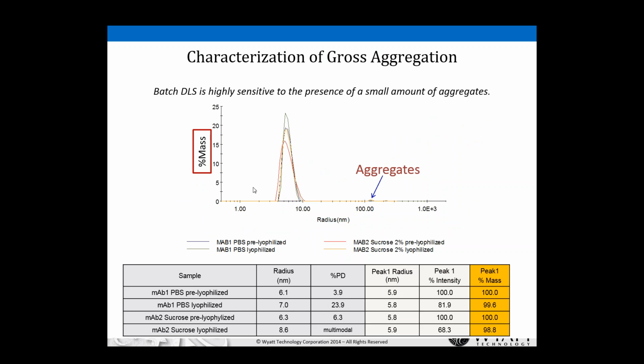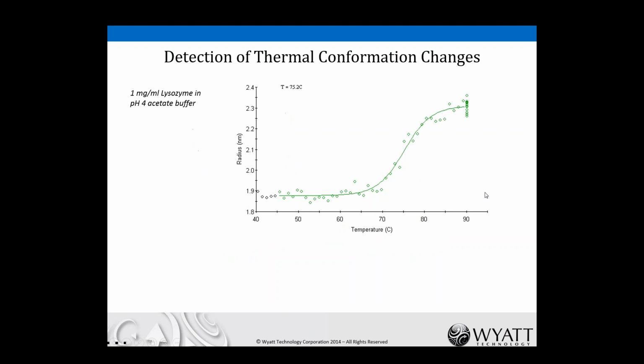The data can be converted to percent mass. Now, I'm not a fan of converting the data to percent mass because there are some assumptions involved regarding the density of the particles and assuming that they're all the same material. But if they are in fact aggregates of the protein, then they pretty much have the same density, and the conversion to percent mass is fairly reasonable. And this is determined in the Dynamics software. We can output for each of these conditions how much of the percent mass was present in each peak. And so, for instance, in the lyophilized PBS post-reconstitution, we can see that the peak intensity was only 82% of the total, whereas the percent mass was 99.6. So only 0.4% of the total mass is actually present in that tiny peak.